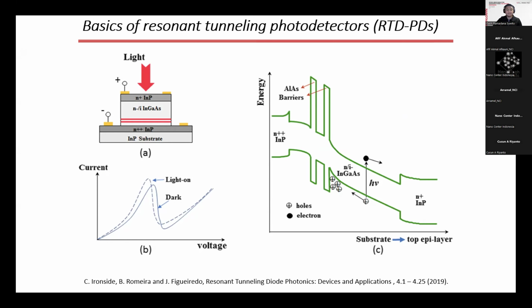So in the dark condition, it acts as a normal RTD. As I said, semi-classically, because of the quantum well, when there is an electron approaching with an energy equal to one of the energy levels inside the quantum well, it will tunnel with tunneling probability equal to 1. So that's why you would get a peak in here.